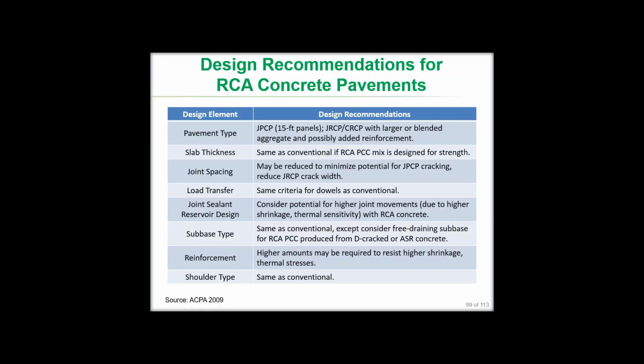Design recommendations, and again, these reflect the consideration of this material as an engineered product, not as a straight-up replacement for natural aggregate. The fact that we may have to reduce our panel lengths a little bit, our slab thicknesses typically will not be any different, because even if we would expect to see perhaps a reduction in concrete strength with the use of a recycled aggregate, and we made no changes, typically there are changes being made in terms of reduced water cementitious ratios or other factors that will still bring us up to the desired strength. So strength and slab thickness usually aren't changed too much.